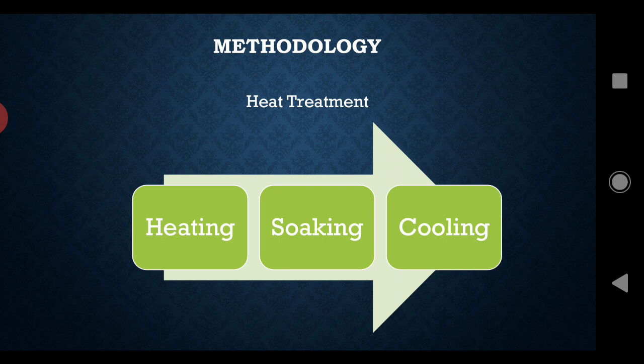So we need to choose the better stainless steel for this testing. Okay, for the heating, prepare the specimen for the first step of the heat treatment, which is the heating process. The specimen is heated to a specific temperature and it will change the material structure.